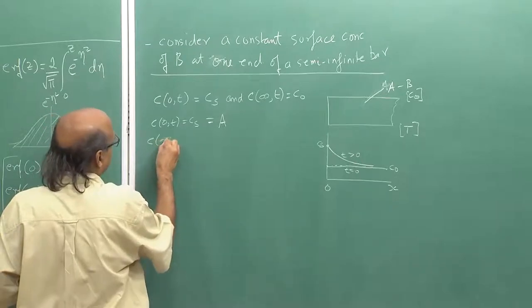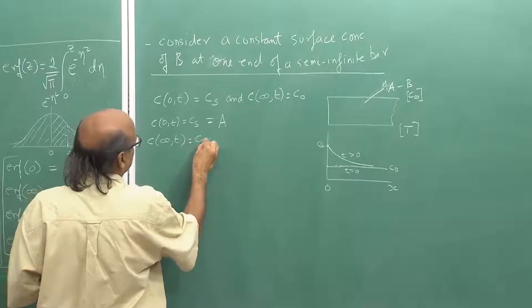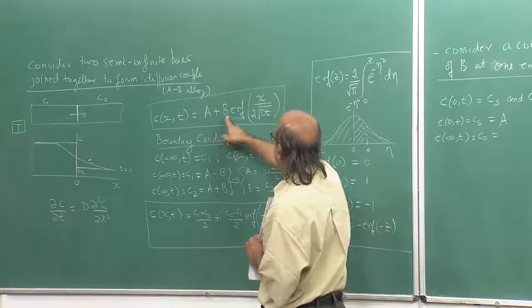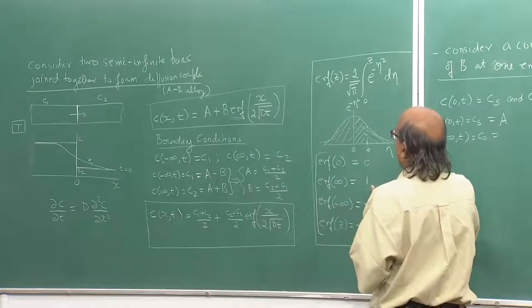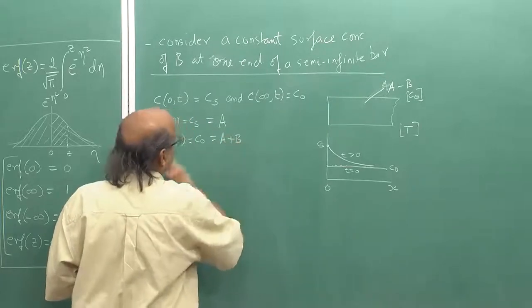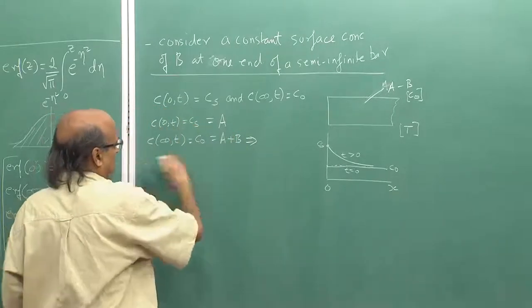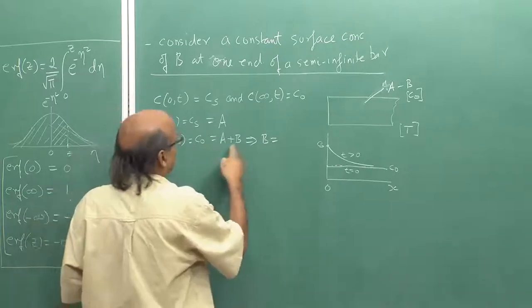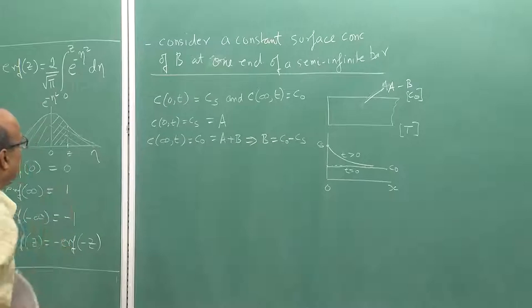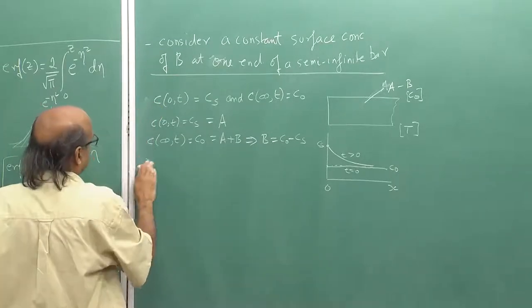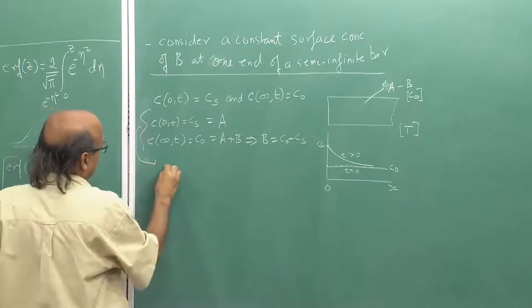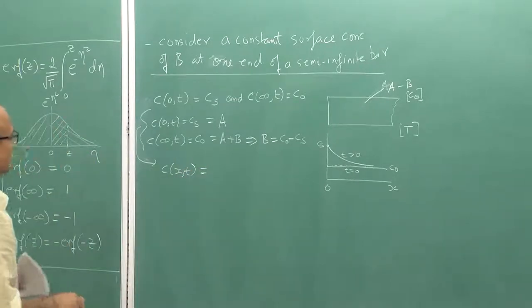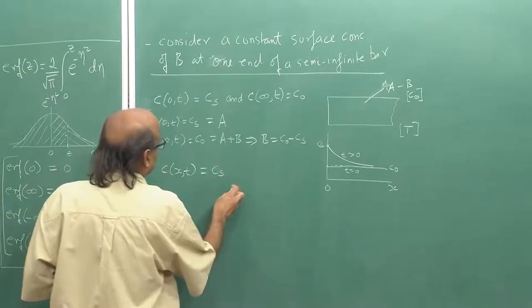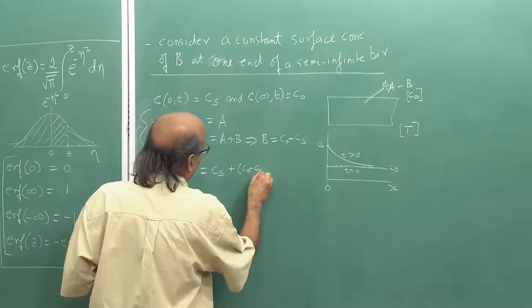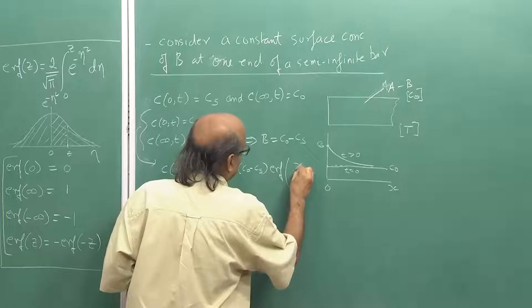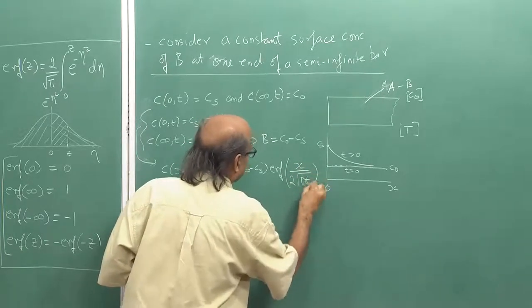Apply the second boundary condition, C of infinity, t is equal to C0, which is equal to, coming back to this solution, A plus B error function of infinity. Error function of infinity we know is 1, and hence C0 is equal to A plus B. From here I already have now A is equal to Cs and B is equal to C0 minus A, or C0 minus Cs. And hence from these boundary conditions I get the solution C of x, t, the concentration profile as a function of distance and time, as Cs plus C0 minus Cs times error function of x upon 2 square root of Dt.